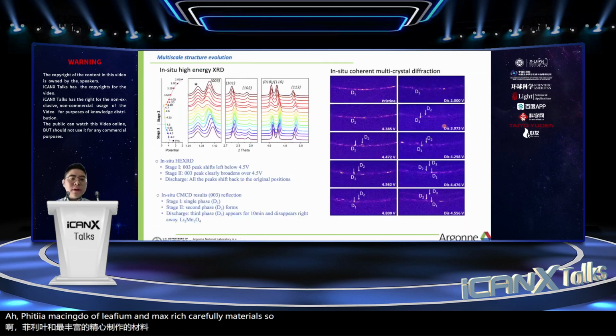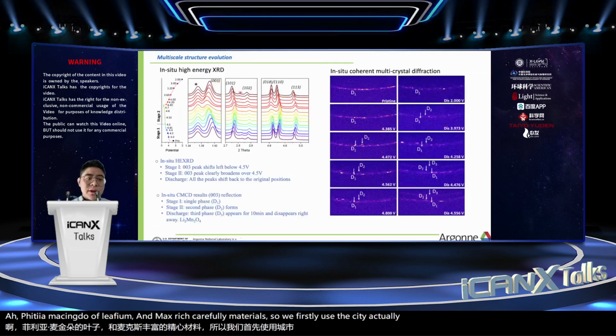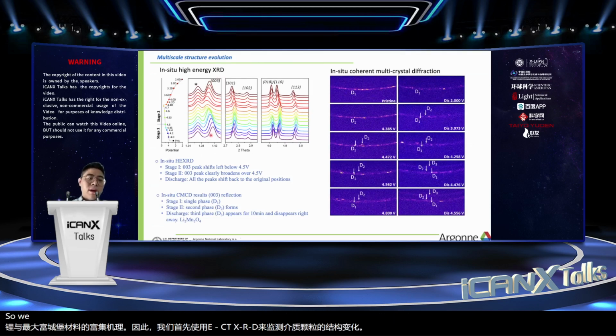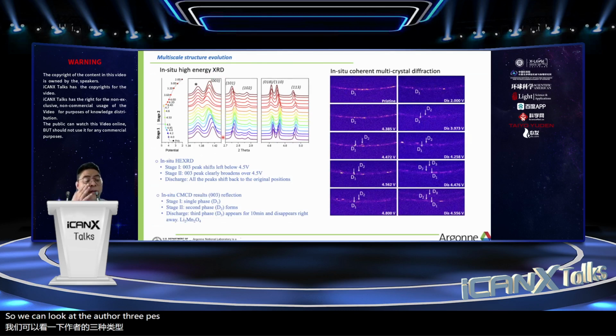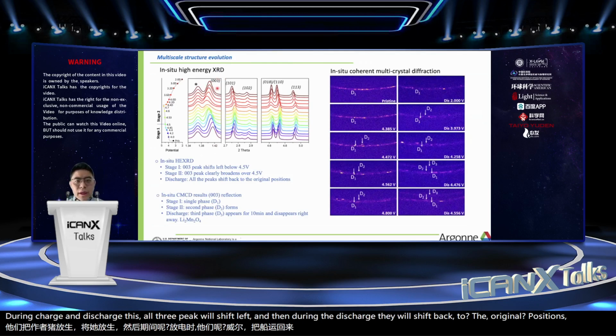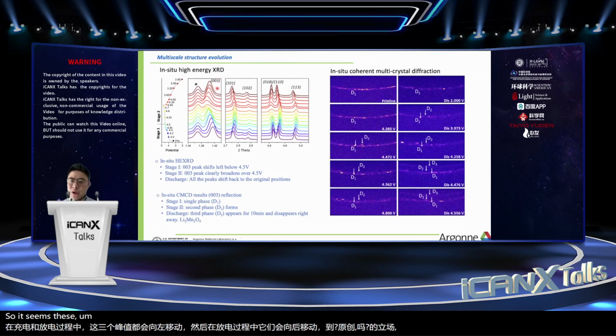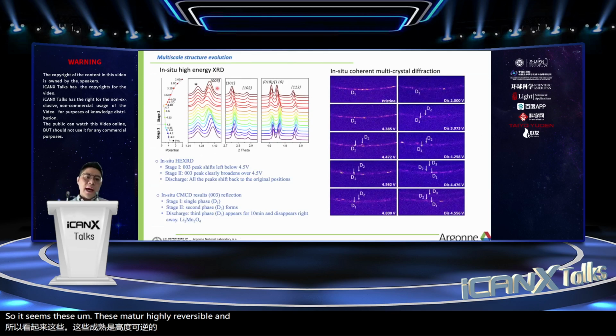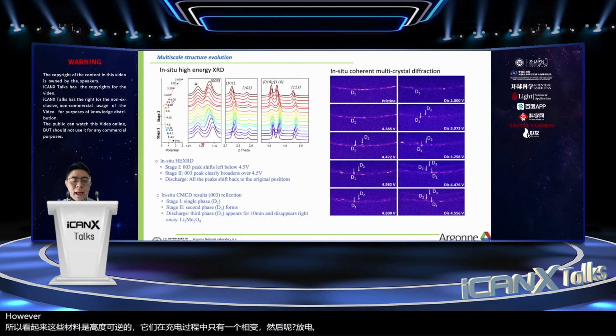So we first use the in situ XRD to monitor the bulk particle structure changes. So we can look at the O3 peaks. We found out this peak is very reversible. During charge, this O3 peak will shift left, and then during the discharge, they will shift back to the original positions. So it seems that these materials are highly reversible, and they only have a single phase transition during charge and discharge. However, this cannot explain why this material degraded so fast, right?